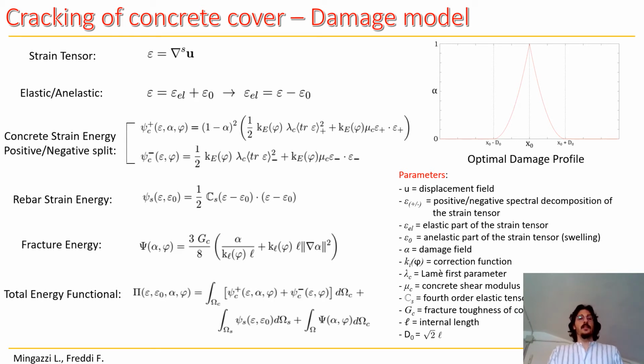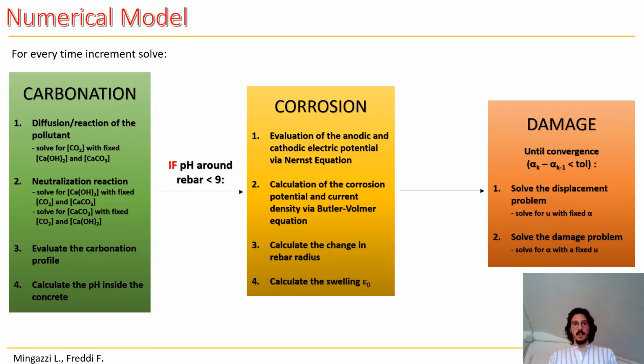It should be noted that for both the strain energies as well as for the fracture energy, the material modulation functions are included in order to account for the changes in the material properties due to the advance of the carbonation front. Lastly, the total energy functional is obtained as the sum of the different energy terms integrated over their respective domains. The complete numerical model is therefore structured as follows.